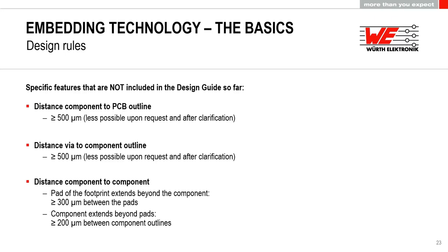If the component is bigger than the actual footprint, for example, for bottom termination components, then we say at least 200 micron between the component outlines. And as always, smaller distance might be possible, but then we again need to have a closer look onto it.